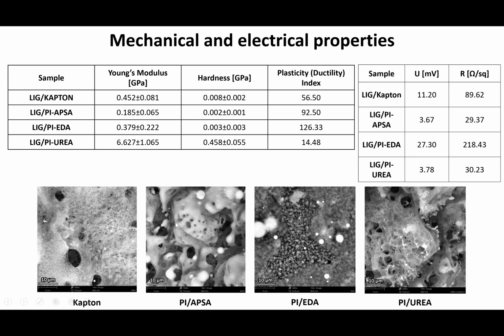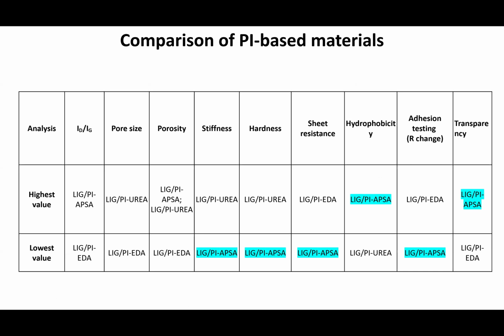And then on the bottom, you see SEM pictures. They all have this nice porous structure. It's a bit harder to see for the EDA sample because this sample has some polymer, thermally degraded polymer due to laser induction on top of the graphene, so it's hard to characterize. And the point is that with tuning this chemistry, you get different properties of the materials.